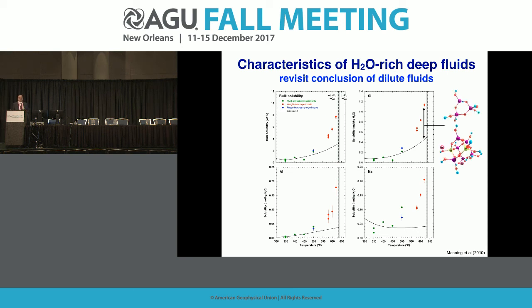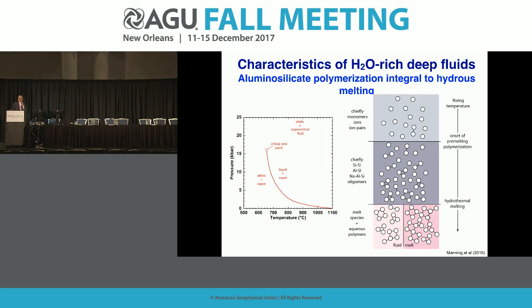And again, that deviation is due to the presence of species that are not taken into account in the calculations, these polymerized species, which in fact constitute most of the dissolved solids. By the time you get to the solidus, the solution is dominated by polymerized species. The ions barely matter at all. This actually motivates a fundamentally different way of thinking about hydrous melting.